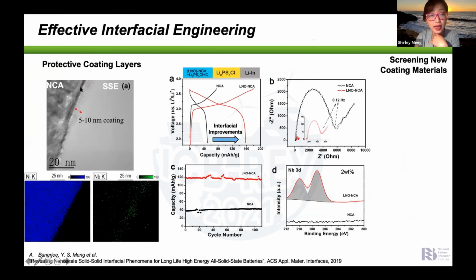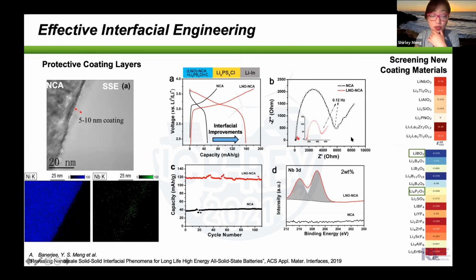We did have good solutions. For example, the cathode can be stabilized with a simple surface coating of lithium niobate, and we can then cycle the batteries a few hundred cycles without any problems. And for the computational work my colleague, Professor Shyue Ping Ong, did, we found borates are also very promising coating materials. So we are able to stabilize the cathode with the LPSCl argyrodite-based solid electrolyte.